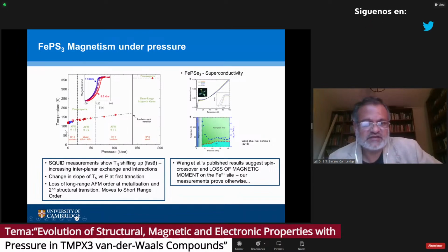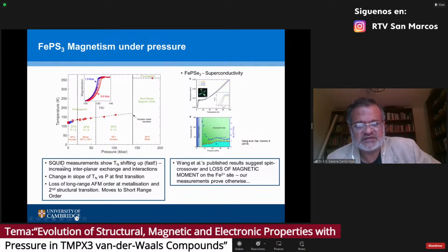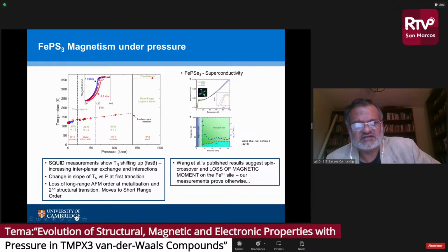All of those data. So here we have the pressure versus temperature phase diagram. First of all, we did some lab-based measurements of magnetism under pressure, and you see some data, but we could only go down to quite an early part of this phase diagram, meaning right here, well before any transition could happen. But what we can establish is that it's a proper antiferromagnet there. With neutrons, we could establish what the propagation vectors were in the insulating state, and then we apply pressure.